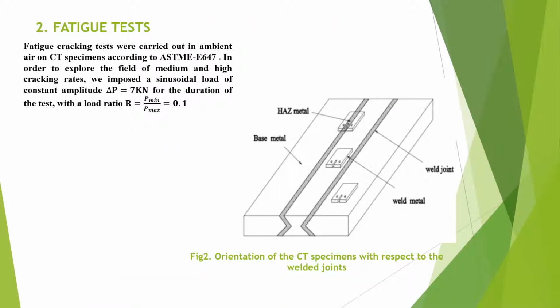The pipe is welded by the submerged arc welding (SAW) process. Fatigue cracking tests were carried out in ambient air on CT specimens. The loading frequency was 25 Hz with a sinusoidal waveform of constant amplitude and constant stress ratio in the three zones studied, as in Figure 2. The results in Figure 3 have shown that the heat-affected zone and weld metal have a significantly higher crack propagation resistance at small delta K values.